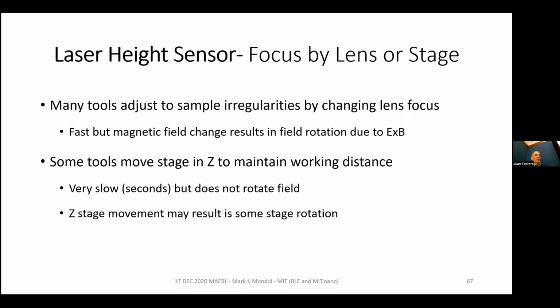There are two ways of changing focus. One way that's used in most tools is we change the current through the final lens, and that changes the focal distance of the lens. Or we can actually physically move the stage up and down. On the Elionix tools, that's what happens. This is very nice in some ways because we get rid of E cross B and some rotational effects that you might get by changing the flux in the final lens. The downside is the stage takes a second to 2 seconds or 3 or 4 seconds even to move up and down, whereas we can change the flux to the final lens much more quickly.